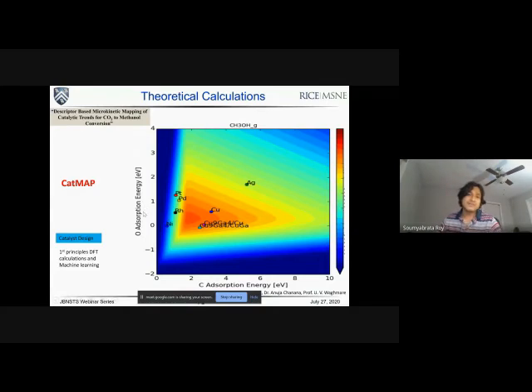And the way we designed the catalyst is that we did this modeling. When you want to make theoretical models to understand the adsorption, or to understand the catalytic efficiency of a catalyst, you plot the oxygen adsorption energy and carbon adsorption energy, because CO2 has carbon and oxygen, and this creates these volcano curves. You can see these triangles, these are called volcanoes. So depending on where your material lies on this, and remember that this oxygen adsorption and carbon adsorption energy can be calculated theoretically without doing any experiments. That means once you develop such a model, if you just theoretically calculate the oxygen adsorption energy and carbon adsorption energy, you can predict whether a material will be catalytically active for CO2 reduction or not.